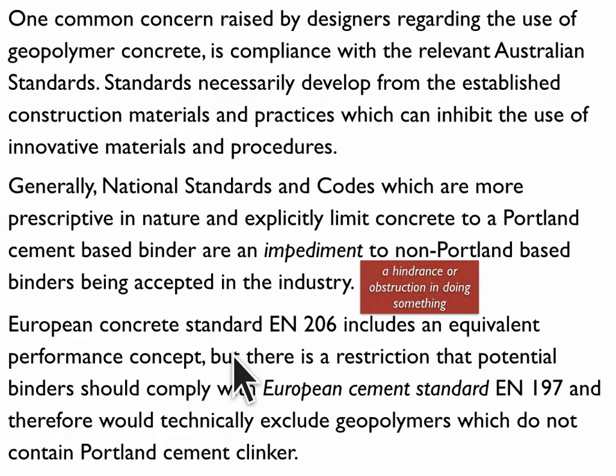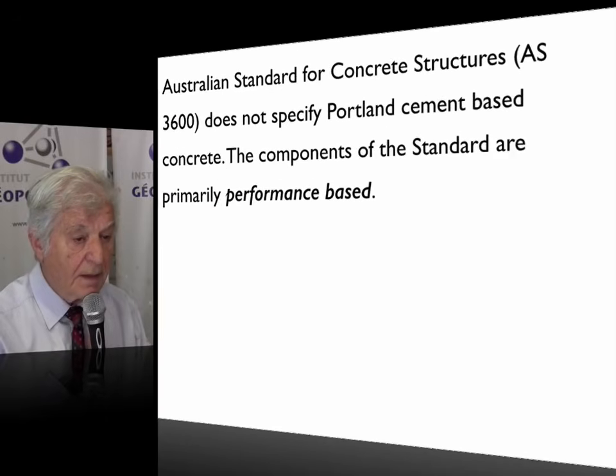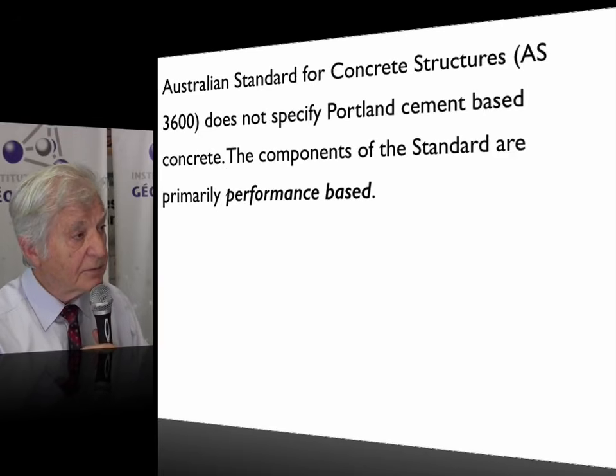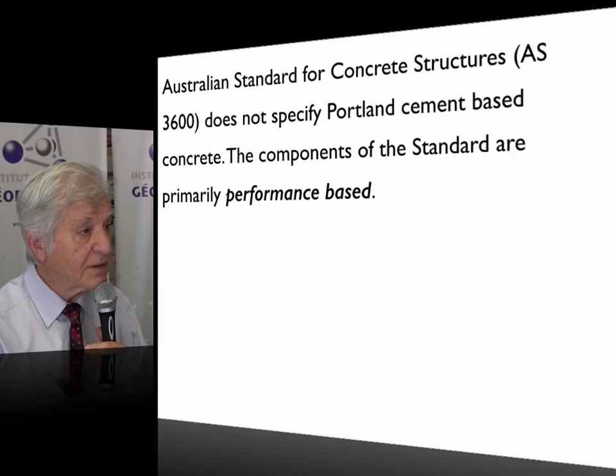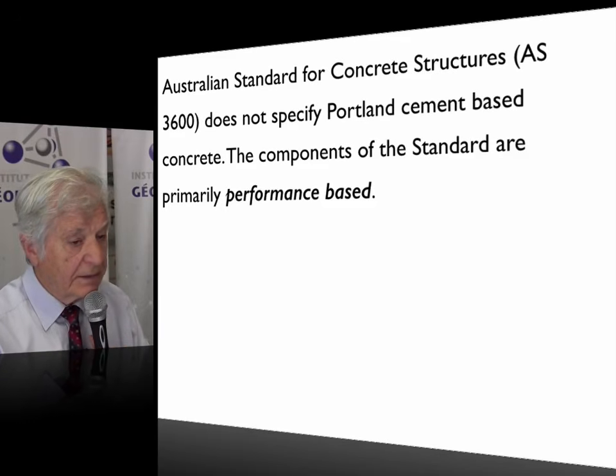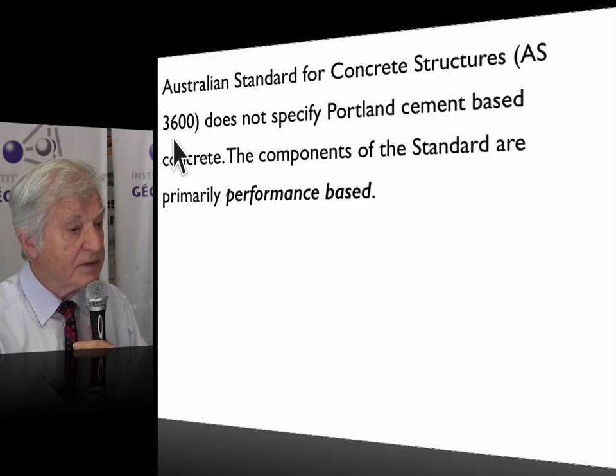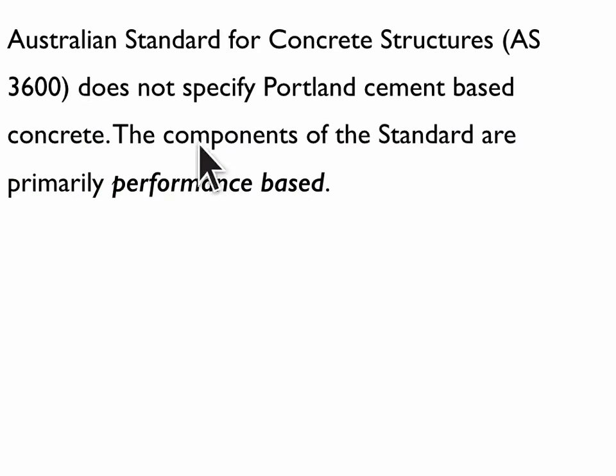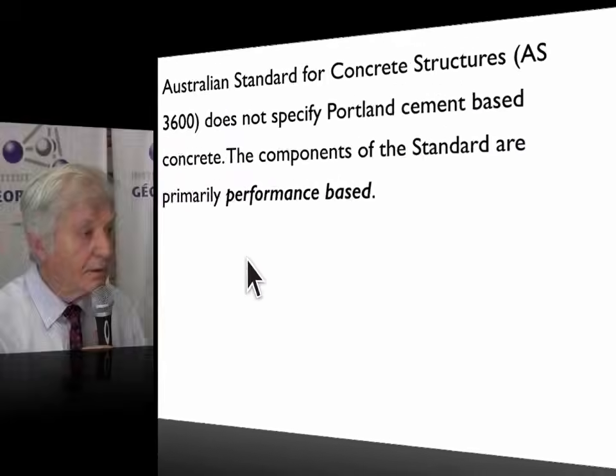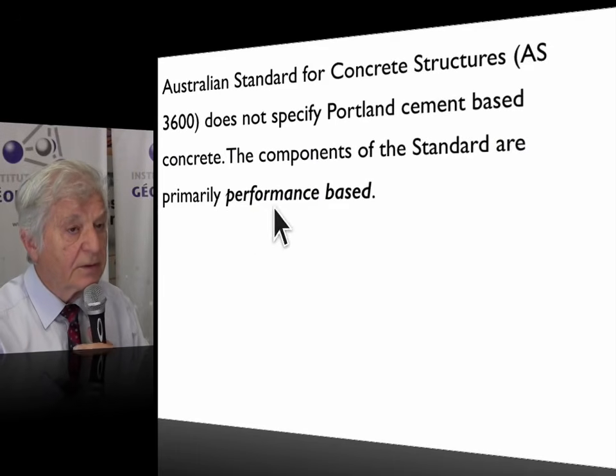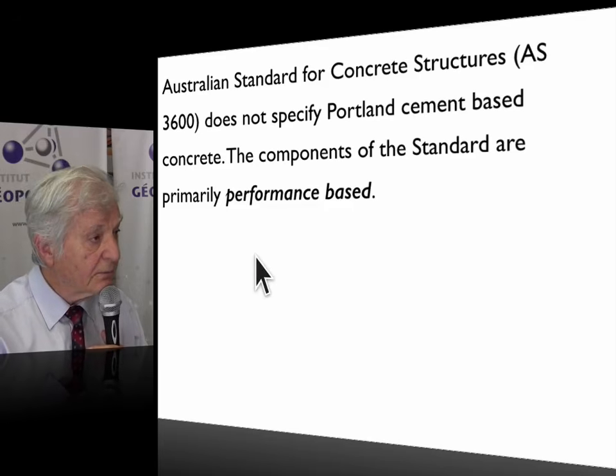The European concrete standard, for example EN 206, includes an equivalent performance concept, but there is a restriction that potential binders should comply with the European cement standard and therefore would technically exclude geopolymers, which do not contain Portland cement clinker. By chance, they found a loophole. They found something totally unexpected. The Australian standard for concrete structures, AS 3600, does not specify Portland cement-based concrete. The components of the standard are only primarily performance-based. So, using this concrete standard, you may use anything provided it provides what is required.